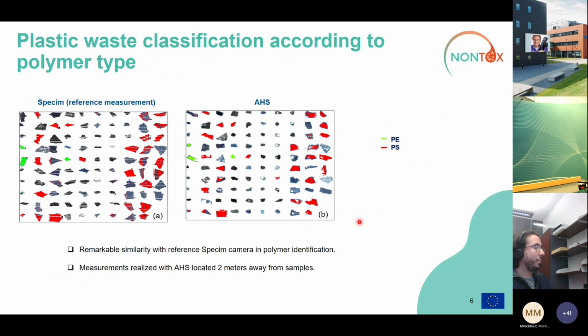And this is another of the main results, which was the classification according to polymer type. So here we see these two images. These are matrices of individual plastic pieces, all arranged to be imaged by both the reference hyperspectral camera and our sensor. So we see here they are colored according to the different polymers. I'm selecting two types of polymer as an example, polyethylene and polystyrene. And we can see more or less the same plastic polymers are being identified in the corresponding pieces. So we can see this similarity between the reference measurements and our own sensor. And more importantly, our sensor can do this at a much larger distance, so it is more suitable also for the recycling environment.